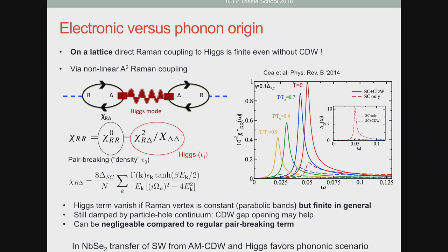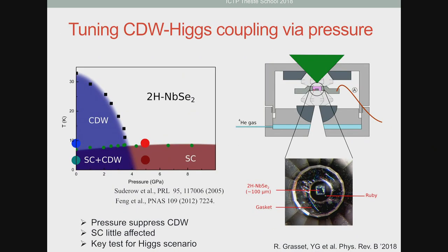Okay, so let's say that the spectral weight transfer favors the phononic scenario, and I'm going to show you experiments under hydrostatic pressure, which also, I think, lend credit to this phononic scenario. The phase diagram of this compound, 2H niobium diselenide, is interesting under pressure. When you apply hydrostatic pressure, you have essentially a suppression of your charge density wave state. But the superconducting transition temperature is very weakly pressure dependent. So by applying pressure, you can kill your CDW state and essentially preserve your superconducting state.